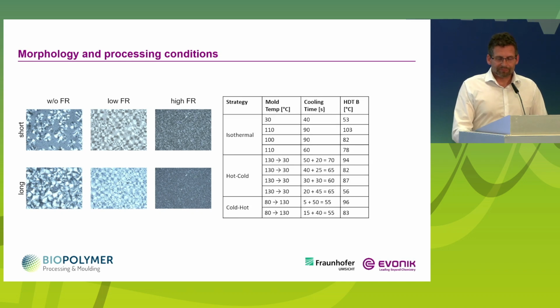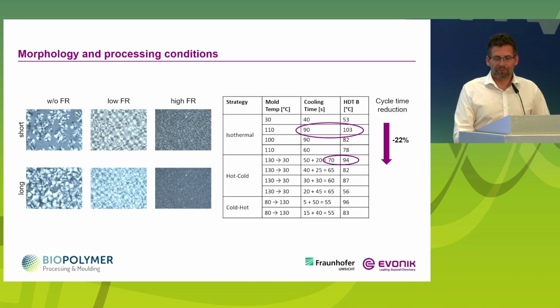And regarding the heat resistance, it's beneficial to process the material at a higher temperature, so at around about the glass transition temperature. And if we increase the mold temperature from room temperature up to 110 degrees, we can double the HDT value, so the heat resistance is higher, but even the cooling time is rising extremely. And therefore we had this approach with a variothermal injection molding processing, that we had the chance to reduce the cycle time down from 90 to 70 seconds, and even lower it down to 55 seconds, and maintain the heat resistance at around about 100 degrees C.